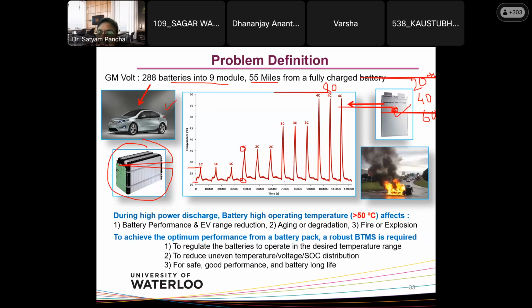If we discharge at 60 ampere constant current discharge, the temperature increases all the way from 20 to almost around 45 degrees. And when we discharge the battery at 4C, meaning the 80 ampere constant current discharge, the temperature is around 60 degrees C.